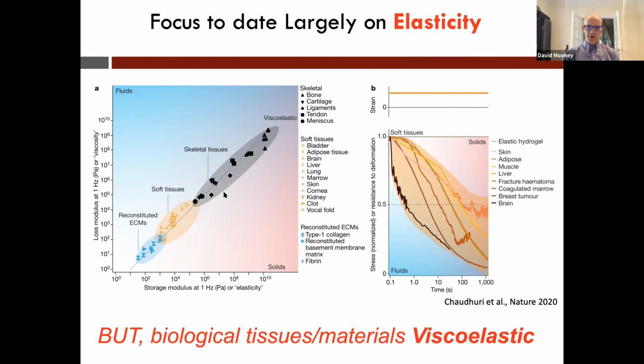Now, in the following slides, I'll also often characterize the effect of the viscoelastic properties by the relaxation time. When a material is viscoelastic, if one applies a constant strain and measures the stress required to maintain that deformation as a function of time, you'll see that it falls as a function of time in a variety of these viscoelastic tissues. In contrast, a purely elastic material won't have any dissipation of energy. But we can characterize this by the time required for half of the initial stress to be dissipated. And basically, the shorter that time is, the more viscoelastic the material will be.